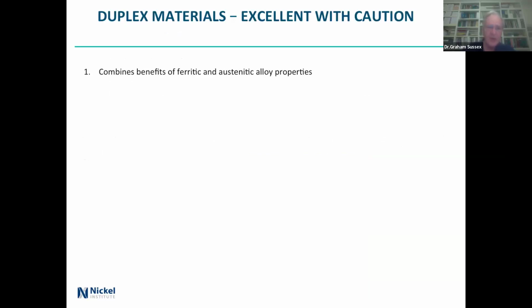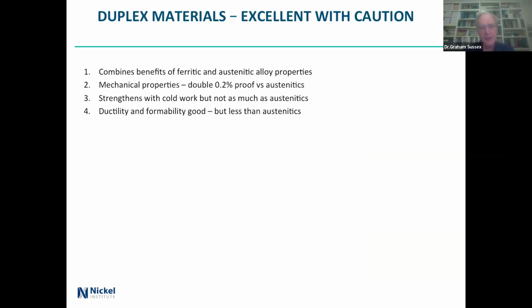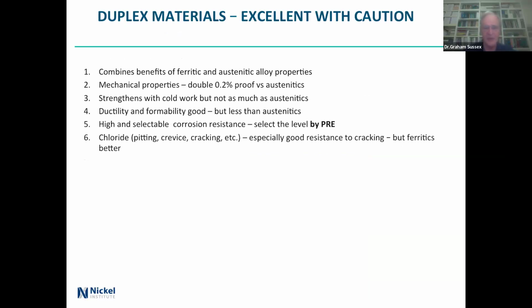What are the advantages? You get benefits from ferritic and the austenitic properties because it's mixed. The mechanical properties, about twice the proof strength of austenitics. Strengthens up with cold work, but not as much as austenitics, so you can get a lot more strength, but you won't do the doubling, for instance, that you might get with an austenitic. Ductility and formability is quite good, but again, a bit less than the austenitics. And you can select the corrosion resistance. You basically put whatever alloy level you want, and you can measure it by the pitting resistance equivalent, and I'll talk about that in a moment or two. Very good against chlorides, pitting, crevice, and particularly against cracking. You have to really work hard to make the duplexes crack, and some oil industry people, of course, do.